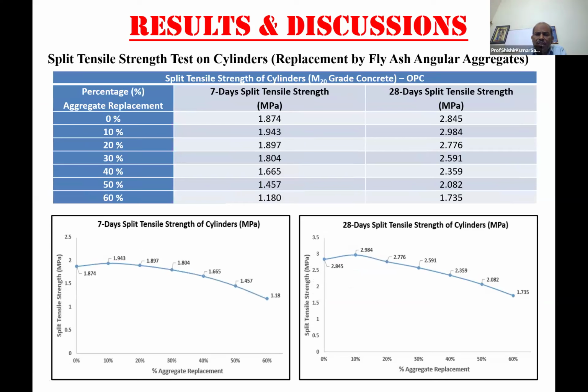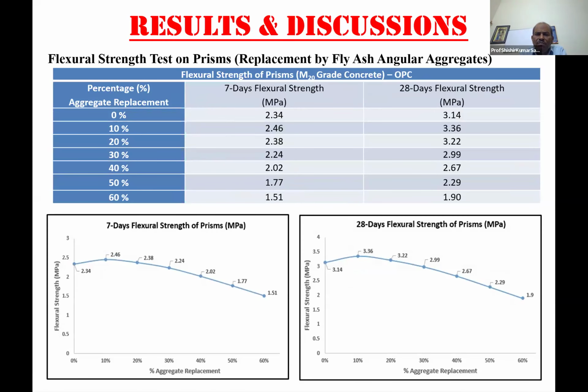Split tensile strength, 10% is optimum. Prism, 10% is 3.36. The 10% is optimum, but the 20% value is also higher than the 0%.